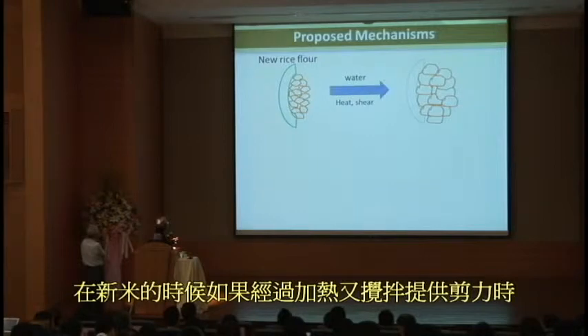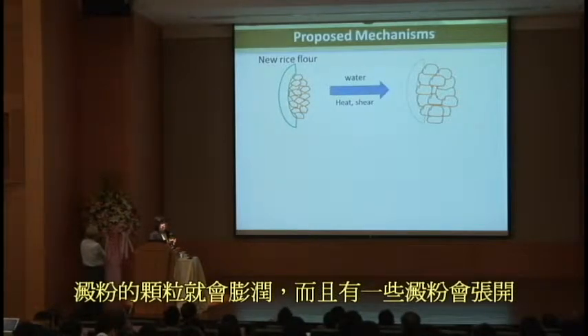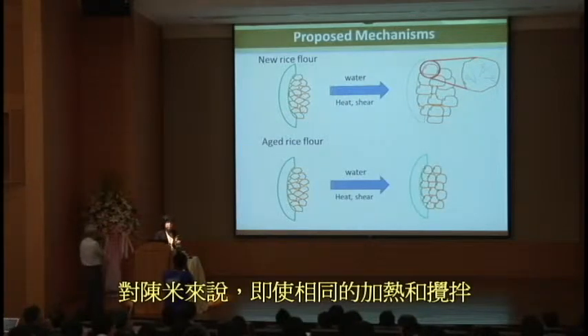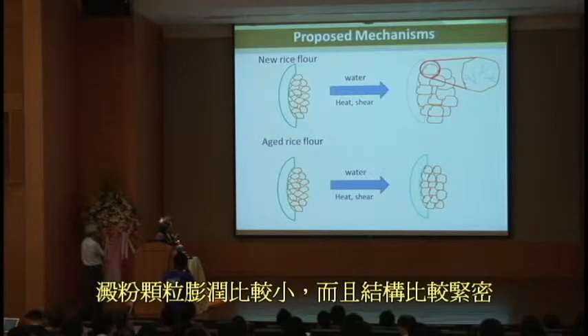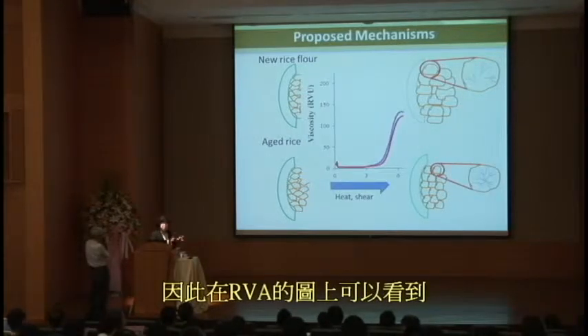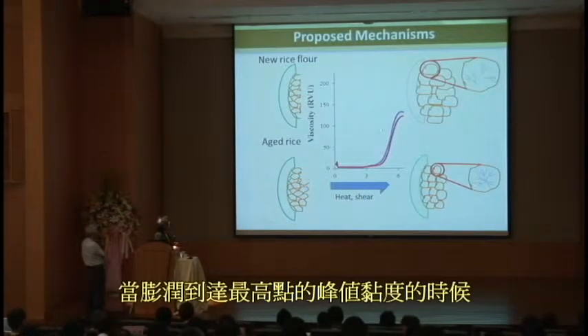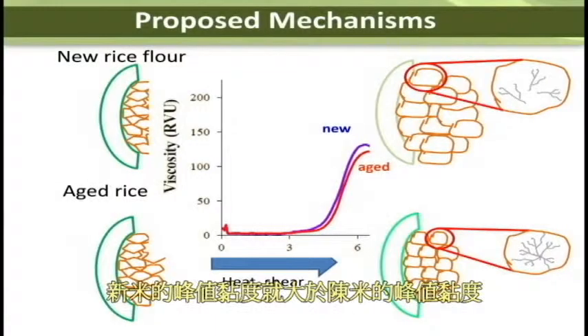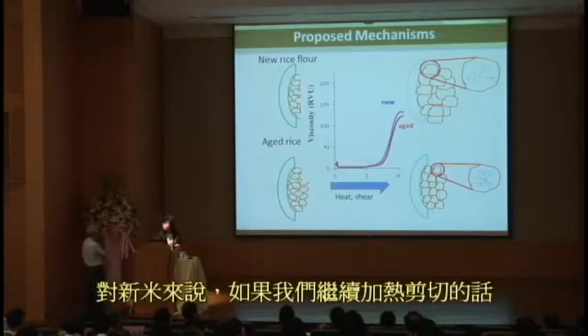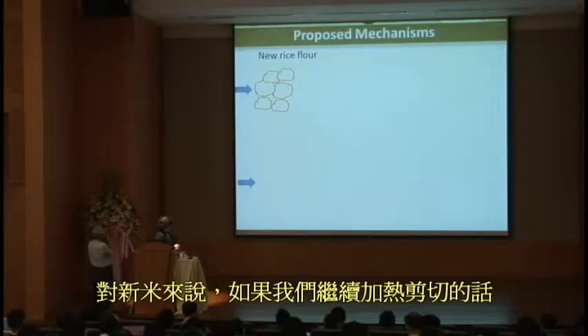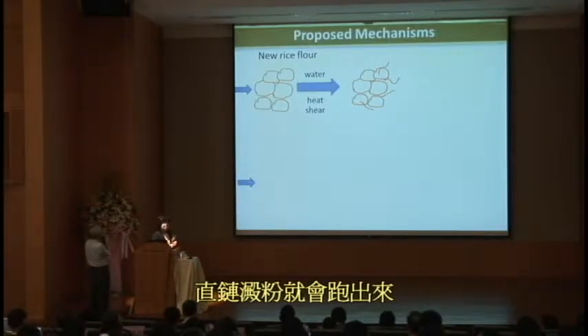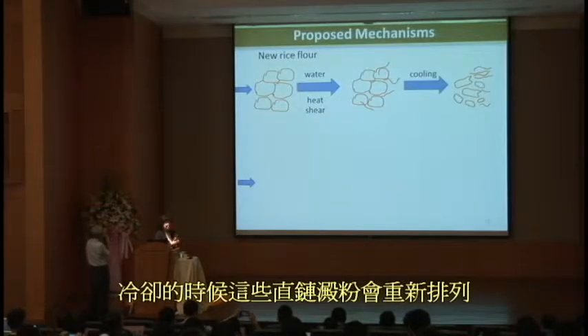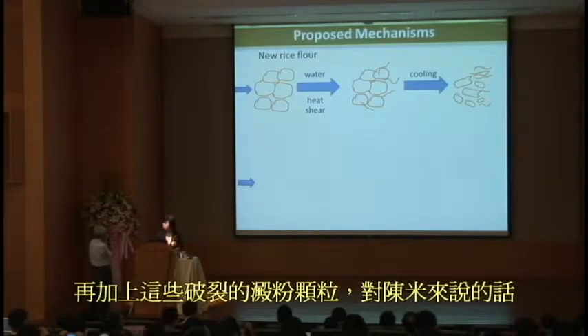For the new rice, with water, heat, and shear, we get swelling of the granule, and the granule is less rigid. But for the aged rice, with the protein and the rigid structure, the swelling is less compared to this one. And this shows in this pasting property, which has the new and the aged rice. The new one, with more swelling, has higher peak viscosity than the aged one. For further analysis, we have more heat and shear. The amylose comes out, leaches out from the granule. And for the cooling, there's some alignment of the amylose and also the disrupted granule.